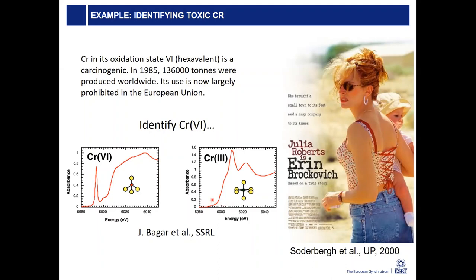And the reason why the spectra are so different is because chromium 6 is 4-coordinated in a tetrahedral local environment. So there's the chromium here in the center and the ligands around. And if it's chromium 3, you have 6 ligands around in an octahedral geometry. Octahedral geometry has a higher symmetry than the tetrahedral symmetry. You have inversion symmetry. In this case, there's no inversion symmetry for a tetrahedral complex.